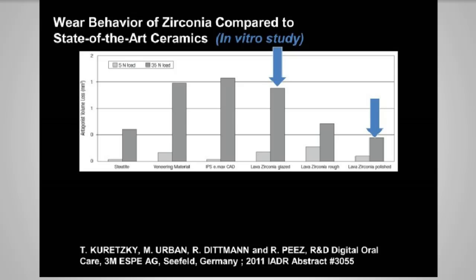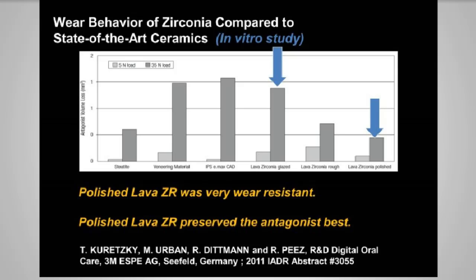What about wear of zirconia? Let's shift gears here a little bit. If we compare glazed zirconia to polished zirconia, and I think many of you know this by now, but here are the studies that have proved this. Polished Lava zirconia is very wear resistant, but it also preserves the antagonist best. If we put glaze over Lava and then we put glaze over, say, e.max, they become the same. The study just shows that glaze will wear the same. So we want to know what the material itself does, because lithium silicate can be used without glaze in occlusal areas, just like zirconia can.